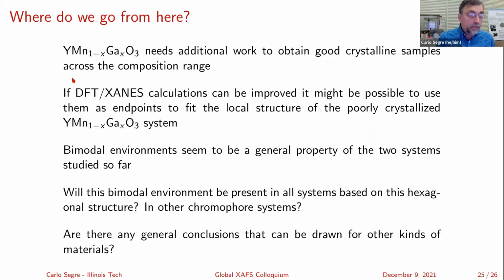If I can do better on the DFT XANES calculations, I might be able to use those calculations as endpoints so that I don't need to have a full range, and I don't need to have the endpoints experimentally to be able to understand what's going on or try to fit the data that I get in EXAFS and XANES. Not clear, but that's my hope, and that's why I'm still interested in working on this.